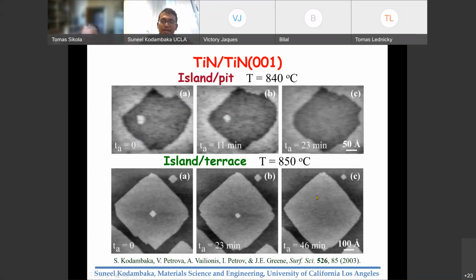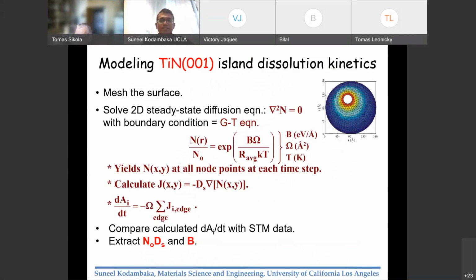In this case, the atoms have to jump down the step edge and attach at this step edge. So they have to overcome an additional barrier, the so-called Ehrlich-Schwoebel barrier. I won't go through the details, but we can precisely model the island decay kinetics from the data, and we can quantitatively fit the experimentally observed behavior.